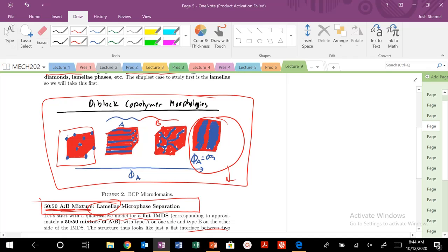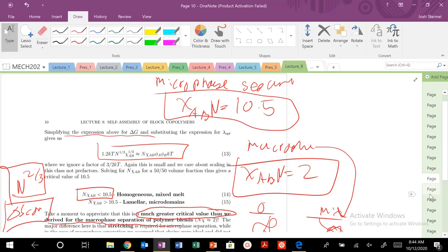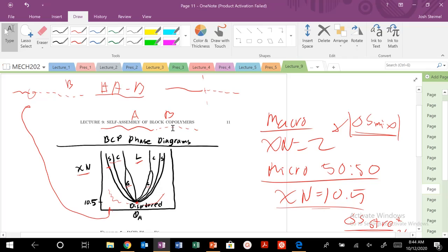But here, we're not only stretched, but we are curved as well. So we're inducing some additional curvature in forming those spheres. Again, there's stretching here, and the number of AB contacts is less. There's some additional curvature pulling, so it's not only elongated or stretched, but one can be compressed, and inducing curvature is very energetically unfavorable in our system. So the delta S of stretching term is probably going to be larger as well. We have larger delta S of stretching, and we potentially have fewer AB contacts. That's what's going to drive this critical chi-n to increase even further.